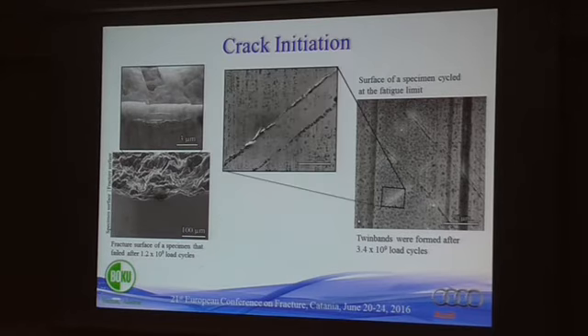So, if you take a closer look at one of these twin bands, you can see these micro cracks emanating from the twin band, and also this debris indicating slip. So, at the moment we cannot answer this question satisfyingly. We have found indications for slip, we have found indications for twinning, so at the moment we just might assume that the crack might be initiated by twin assistance. But we'd like to conduct further investigations on the subject.